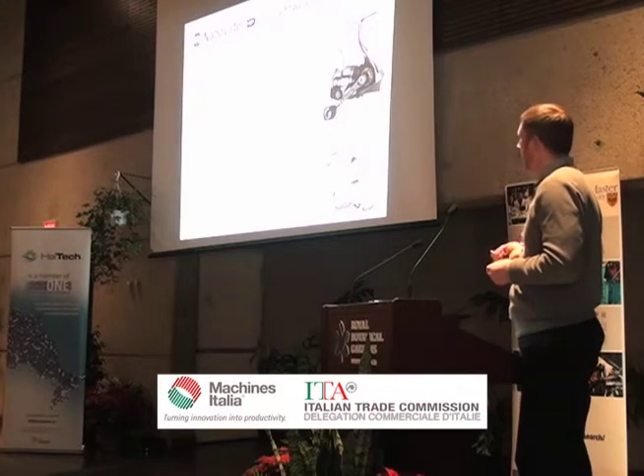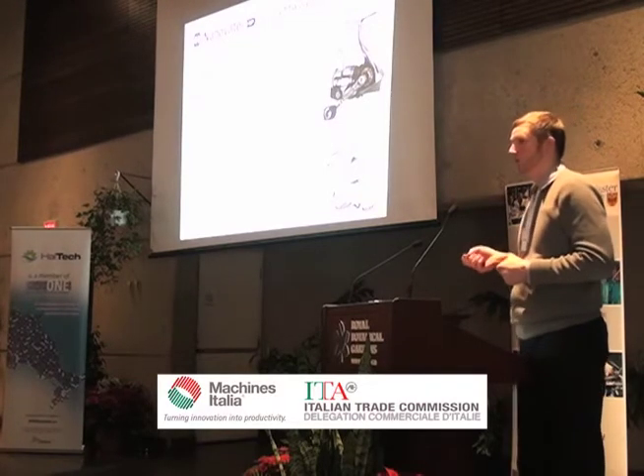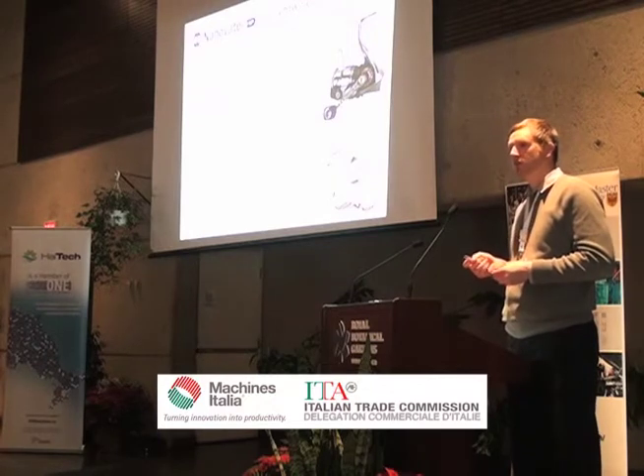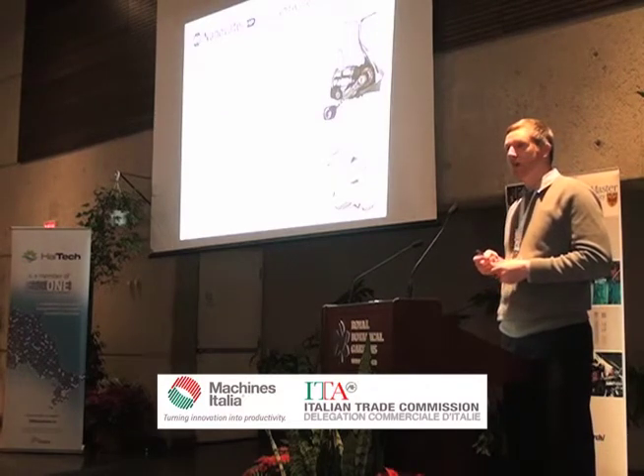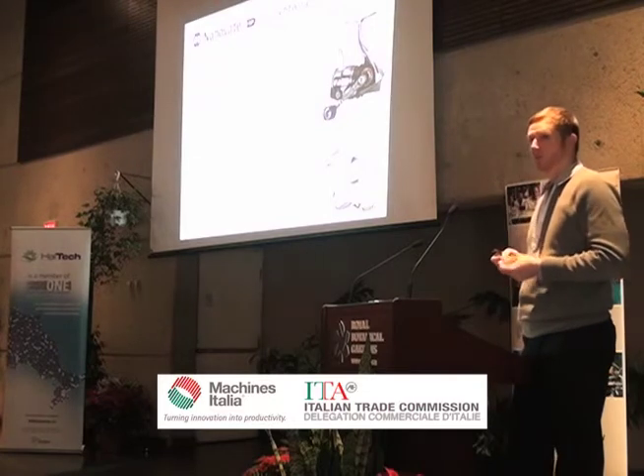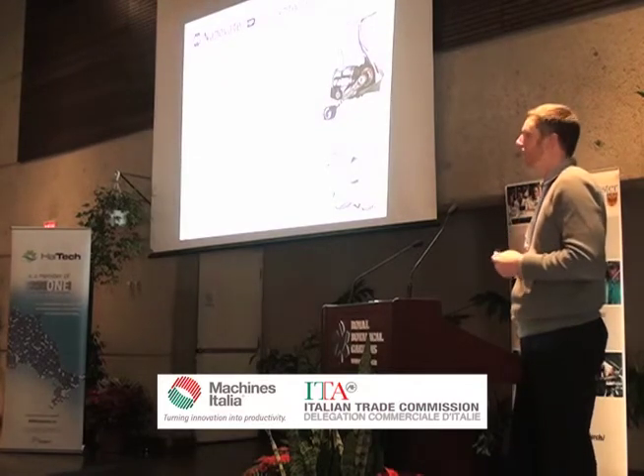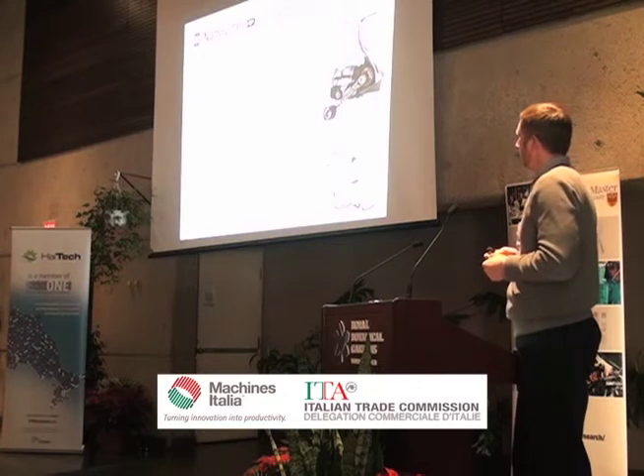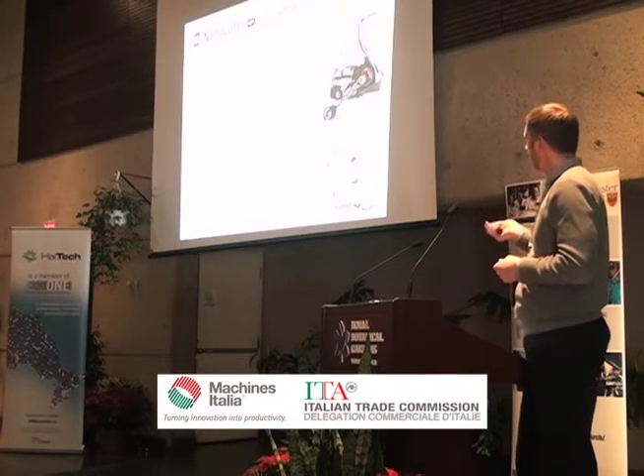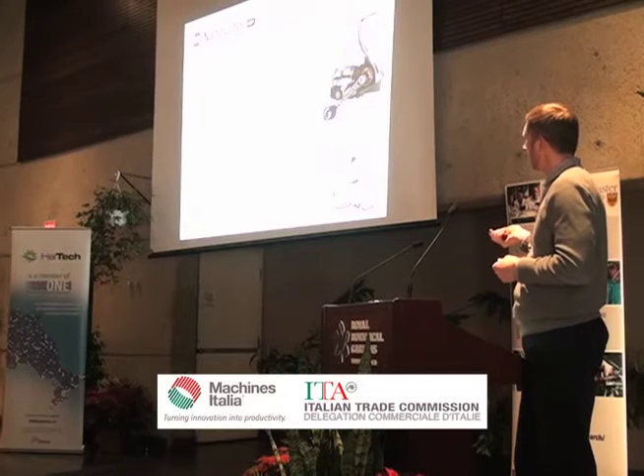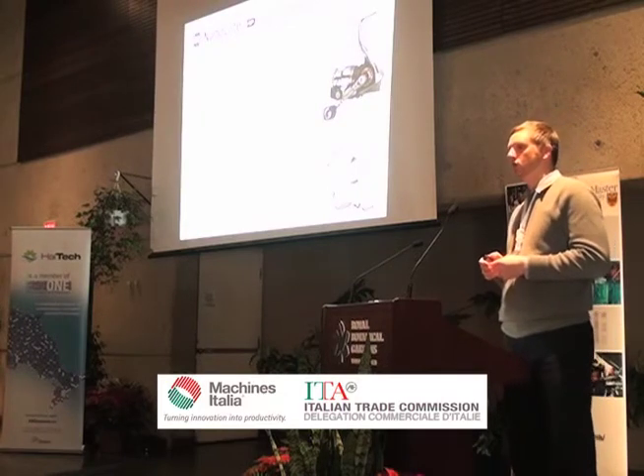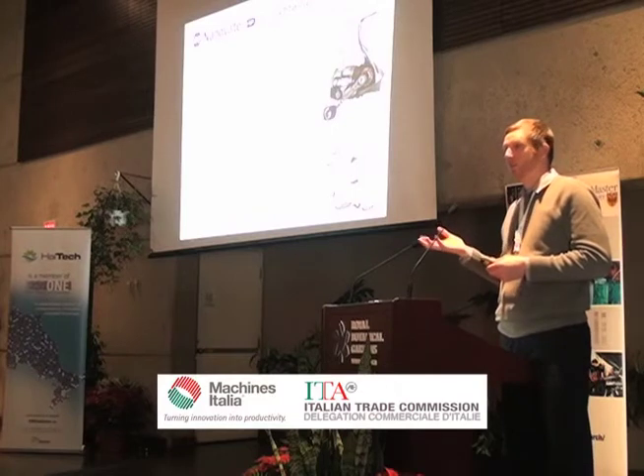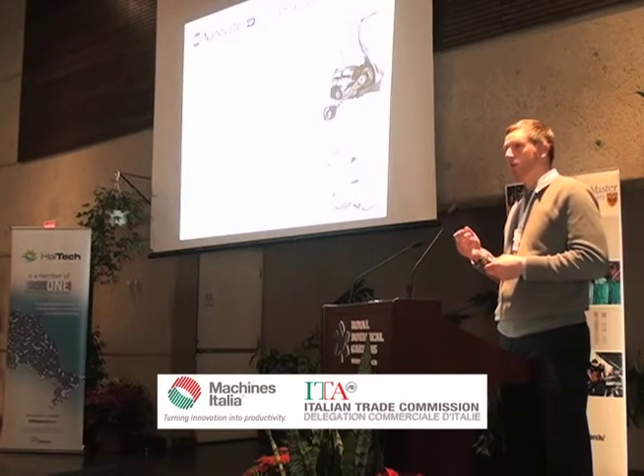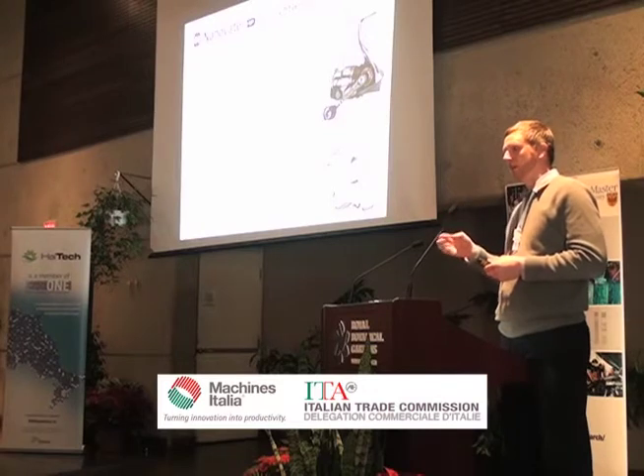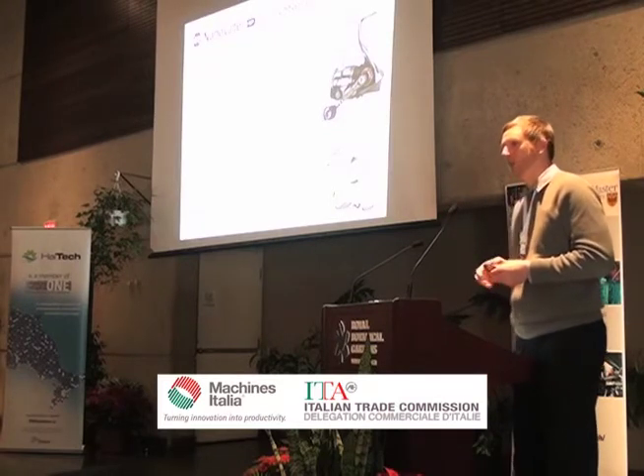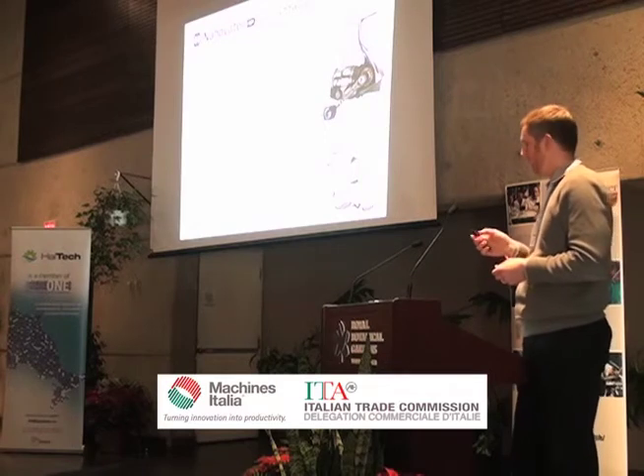But you have added benefit because you have a surface hardness close to tool steel. We're talking about material that has hardness between about 50 to, in some cases, 65 Rockwell C hardness. So it's a very durable material, scratch-proof, dent-proof, impact resistant. So when you compare this to something like an anodized aluminum, that's good, but that hard anodized layer can break down, and when it does, you're exposing the aluminum underneath, whereas our material has hardness, but it's also got toughness, so it stays around and it can absorb a lot of energy before breaking away.